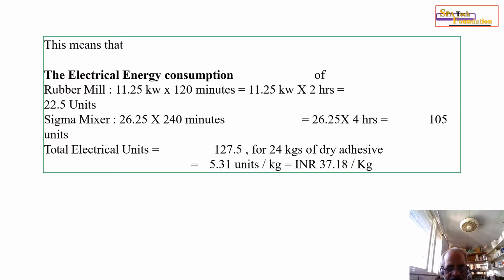This means the electrical energy consumption of the rubber mill at 11.25 kw for 120 minutes is equal to 22.5 units. For the Sigma mixer, the consumption will be 26.25 into 240 minutes, which is equal to 105 units. Total electrical units consumed 127.5 for 24 kgs of dry adhesive, that is 5.31 units per kg, which will be roughly around 37.18 rupees per kg.